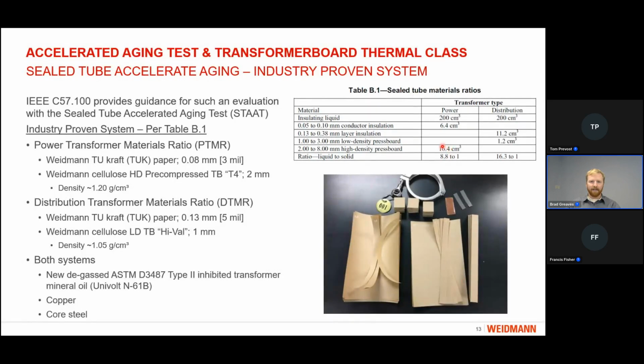This materials ratio has conductor insulation, which in our case is Weidmann thermally upgraded kraft paper. And we have high density pressboard, which again is Weidmann high density pre-compressed T4. We then look at the distribution materials ratio, where we see slightly different materials as well as different ratios. In this case, we have what's considered layer insulation, slightly thicker, same density, but still thermally upgraded kraft paper. And then we have low density pressboard, in our case, Weidmann Hi-Val, slightly lower density than our T4.